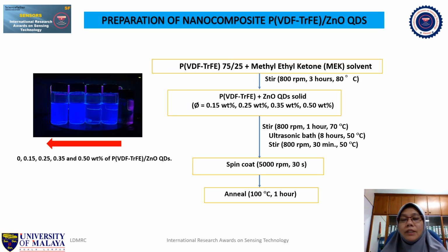To prepare a nanocomposite of PVDF-TrFE with zinc oxide quantum dot, initially we prepare the PVDF-TrFE solution by dissolving it inside methyl ethyl ketone, and after that we add zinc oxide quantum dot solid into the PVDF-TrFE solution. We vary the weight percentage of the zinc oxide quantum dot from 0.15 weight percent to 0.5 weight percent. This solution will be stirred in an ultrasonic bath and stirred again before it is spin coated at 5000 RPM for 30 seconds, and afterwards it will be annealed for 1 hour at 100 degrees Celsius.